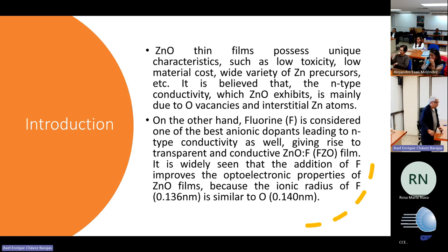Previously, I want to mention that fluorine doped zinc oxide is an issue that had not reached a satisfactory solution until our team reported the requirement of aging time of the solution. In this case, conductivity decreases as the aging time increases, reaching saturation. The quest is to deposit quality TCO with a fresh solution.